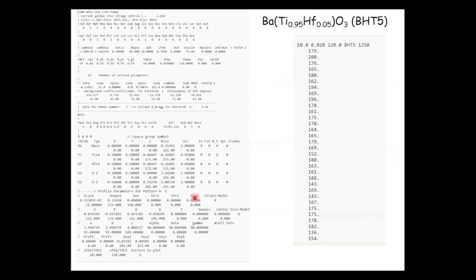So you can see this is for barium titanate. So here what I have done, this is 95% titanium, 5% hafnium. So here occupancy I made 0.95 and 0.05, but otherwise positions are the same. Only occupancy: 95% titanium will occupy, 5% hafnium will occupy. Otherwise, if you match these numbers, they will be the same everywhere.